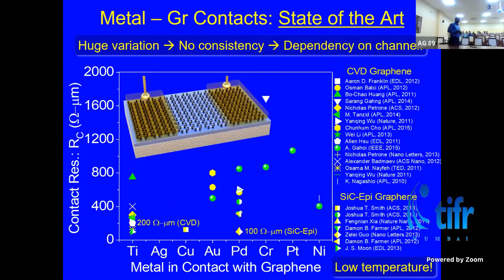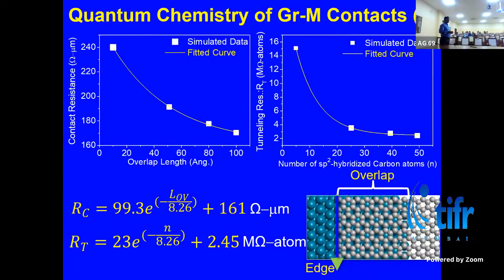Now I'll come back to graphene, and in case of graphene, these were the best numbers reported, and these were all 4 Kelvin measurements, right? But the real world does not work at 4 Kelvin, right? So when we started investigating, we first did certain computations, DFT and GF, to understand these systems better, and then derive experiments out of it.